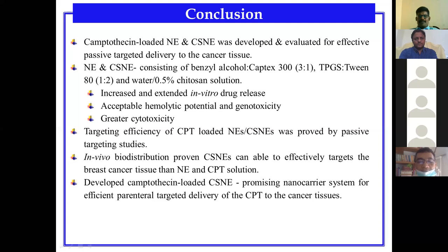Sir, we can use a simple process called ionic gelation. You dissolve your chitosan in dilute acetic acid to make a solution, to which you add tripolyphosphate and allow them to interact. Due to the ionic interaction, a precipitate of nanoparticles forms. That precipitated nanoparticulate system can be centrifuged and washed and then obtained as nanoparticles. It's the simplest technique. There are a lot of techniques, such as polymerization or microemulsion techniques, but simple ionic gelation or precipitation can be utilized very well for preparing nanoparticles from chitosan.